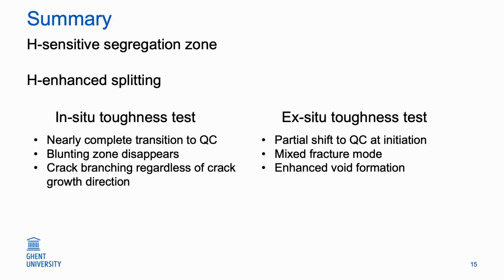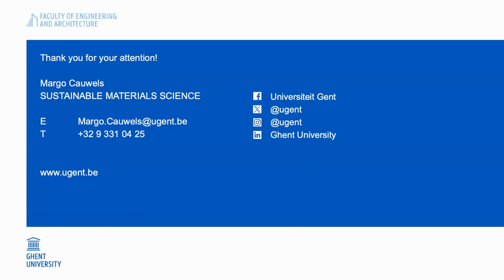For the ex situ tests, we can see a partial shift to quasi-cleavage in the blunting zone, so clearly the crack initiation is affected, and the crack zone is a mixed fracture mode, and we also see the enhanced void formation in our X-ray CTs. With that, I thank you for your attention.